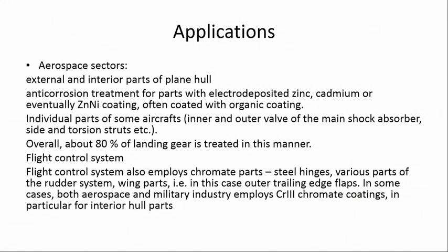And like anti-corrosion treatment for parts with electrodeposited zinc, cadmium or eventually zinc nickel coating, after coated with organic coating. So, in individual parts of some aircrafts, 80% of the landing gear is treated by chromate conversion coating. In flight control system, it also employs chromate parts. So, chromate conversion coating was having several applications in the past, and even now, where it has to be coated with other paint, and where the application area is not really in the environment, particularly somewhere that the drainage of the solution is not a problem, there you can always apply the chromate conversion coating.